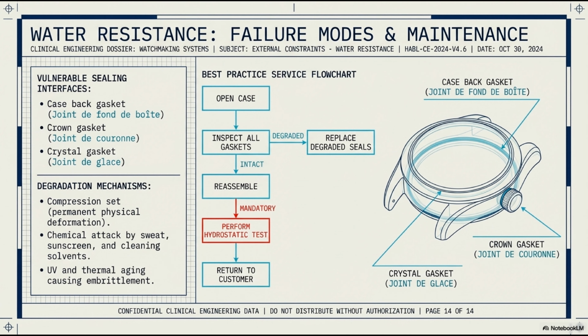How do they fail? Look at the degradation mechanisms. The primary killer is compression set. Over time, the rubber gasket suffers permanent physical deformation. It loses its elastic memory and stops pushing back against the steel walls. Secondary killers include chemical attacks by human sweat, sunscreen, and the very cleaning solvents watchmakers use. Thermal and UV aging also cause the rubber to embrittle and crack.